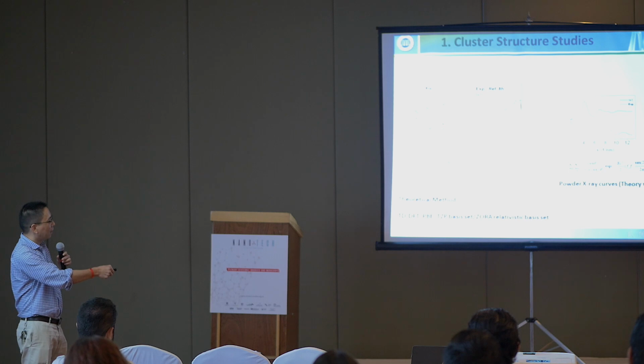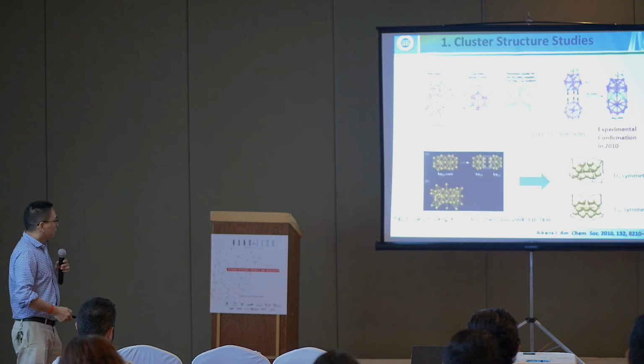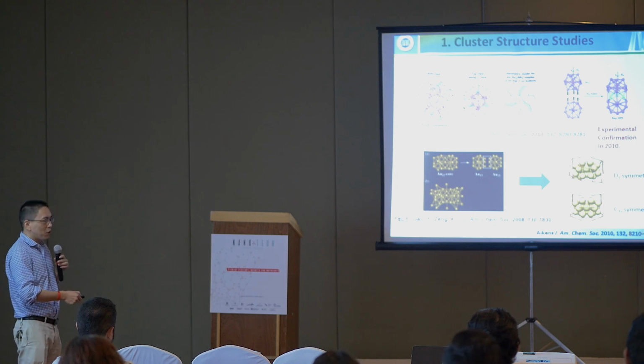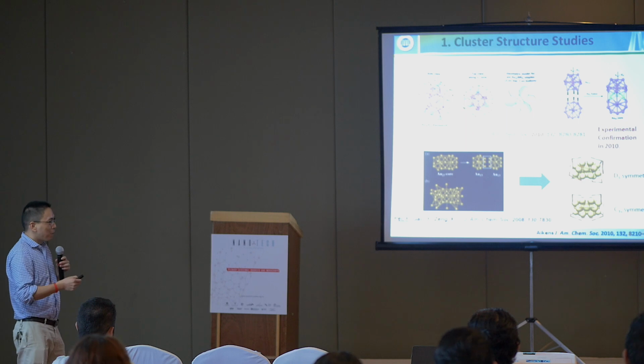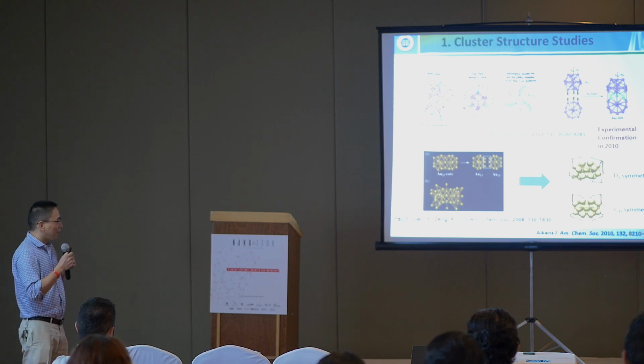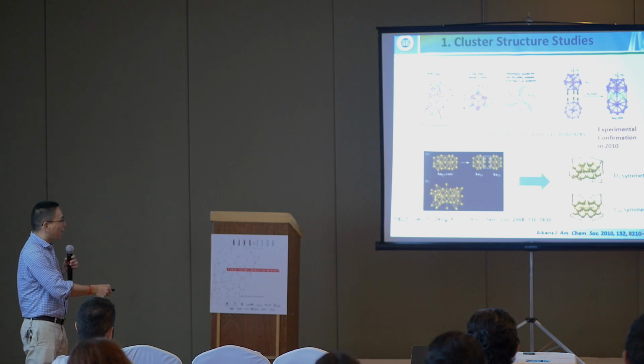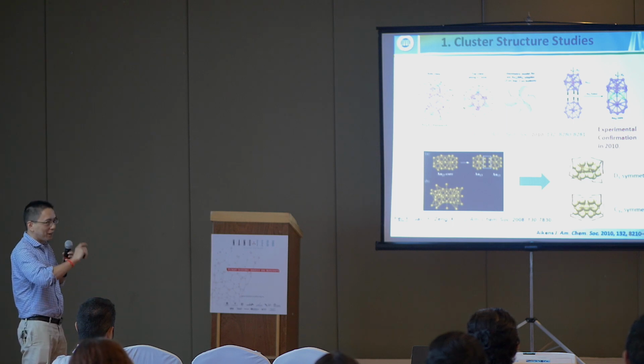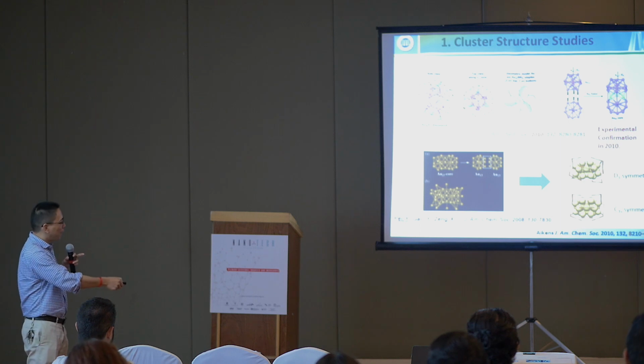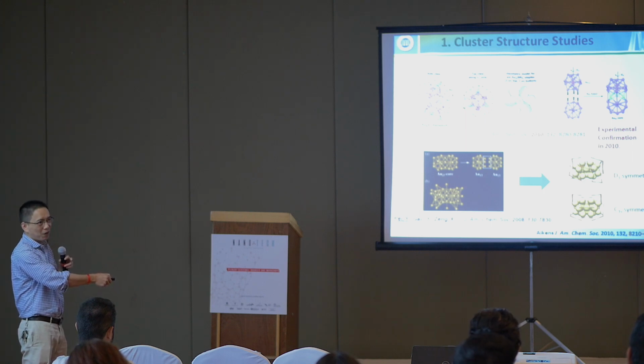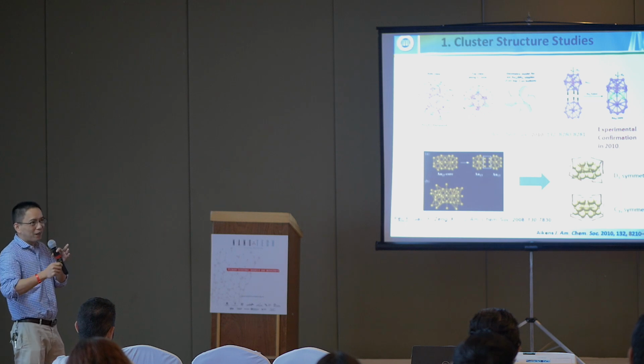And the right one is a comparison of powder X-ray curves. The black line is the experimental one, and this is the theoretical prediction. So after two years, we report the cluster structures. Here, I need to mention that there is a drawback in my predictions. We wrongly predicted the orientation of the ligand. We predicted that the whole cluster has C3V symmetry, but actually it is D3 symmetry. The ligand rotates by 30 degrees.